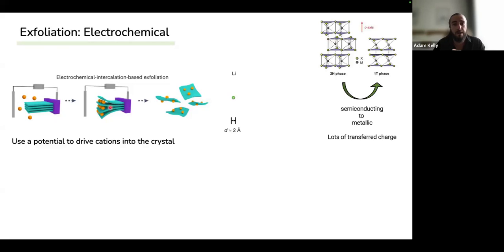So this was first done maybe 10 years ago with lithium, for example, because this is a very, very small ion. However, the problem is when you use lithium, you get an awful lot of these lithium ions. You get lots of them that go in between the layers. And because of the charge transfer from the lithium to the crystal, you actually get a change of phase. So if you have a material like molybdenum disulfide, for example, this will convert from the 2H phase to the 1T phase, which means you no longer have a semiconductor, you have a conductor. So this is no good if you're trying to use this material to make things like transistors.